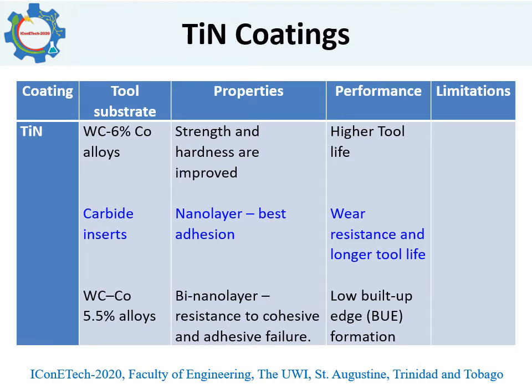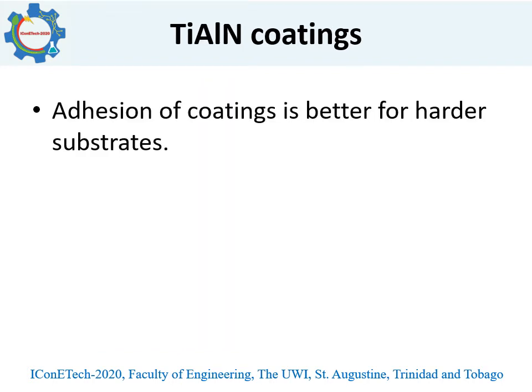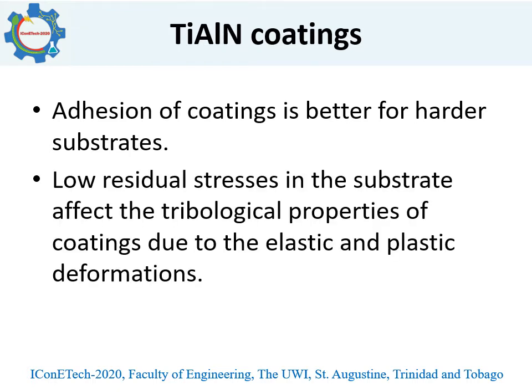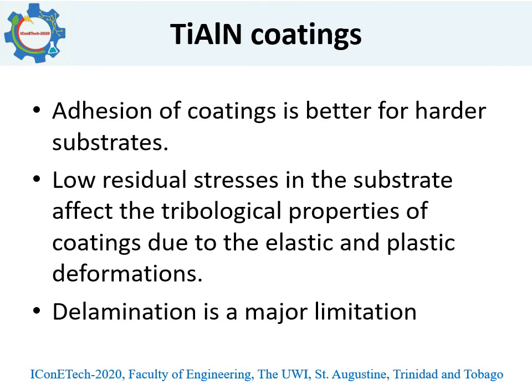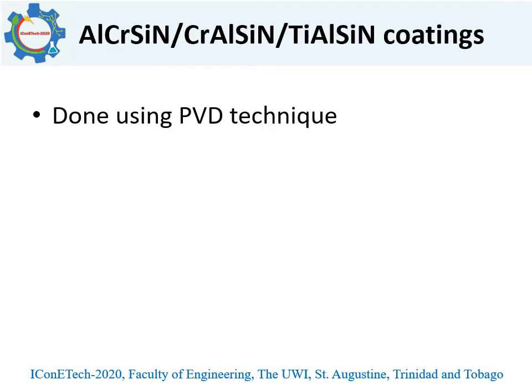You can also add, by nano layers, resistance to cohesive and adhesive failure, because these contribute to lower built-up edge. With multi-layer coatings, adhesion will get improved, particularly if you have harder substrates. So the intermediate layer helps in the adhesion of the coatings. Generally, the substrate should have lower residual stresses. Otherwise, the tribological properties of the coatings are likely to be affected by the elastic-plastic deformation of the substrate. So that should be avoided. And one of the major limitations of these multi-layer coatings is delamination. So we need to look at them.